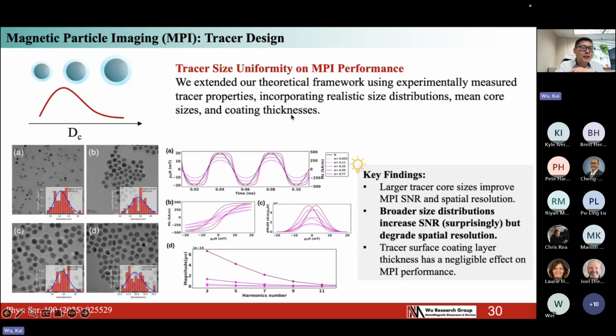Okay, so this slide is about the MNP tracer size, where we vary the MNP diameters from small size to large size, and also we consider that the particles are not uniform in size. They follow a log normal distribution of the nanoparticle size. With considering the particle size and the size distribution, we found that larger nanoparticles will improve the SNR and the spatial resolution in MPI imaging, as we covered in previous slides. If the particles are not uniform, with a broader size distribution, surprisingly, it will increase SNR, but it will degrade the spatial resolution of the imaging. This is because if the particles have a broader size distribution, the larger particles' signal will dominate. They will create a larger signal compared to the smaller particles. So this is something that should be considered when people are using nanoparticles for imaging applications.